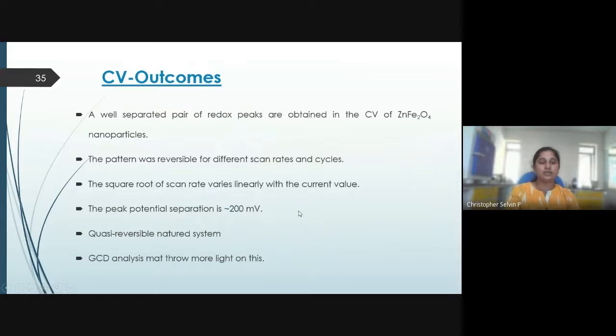And these are the outcomes of CV I would like to highlight. A well-separated pair of redox peaks is obtained for this particular system. The pattern was reversible for different scan rates and cycles. The square root of scan rate varies linearly with the current value, and the peak potential separation is approximately 200 millivolts. So all these points match the requirement for the reversible nature of an electrochemical system. Based on these observations, we can correlate a quasi-reversible nature of this particular electrochemical system. However, we have to go for GCD, that is charge discharge analysis, which may throw more light on this particular behavior.